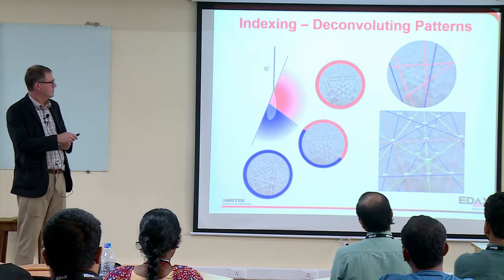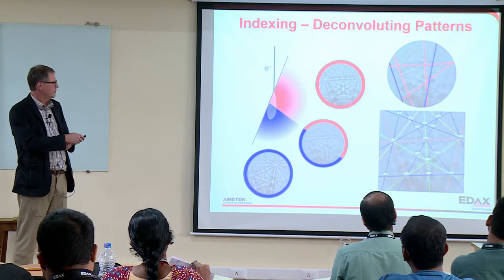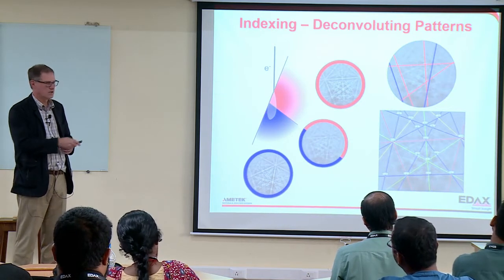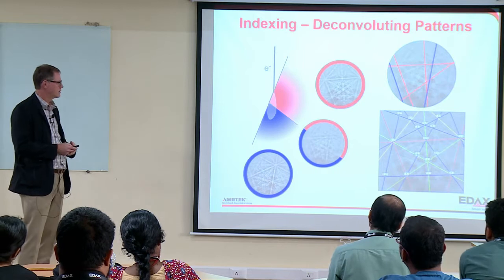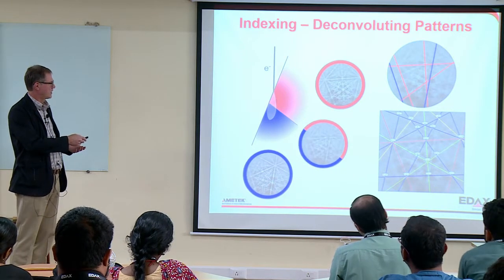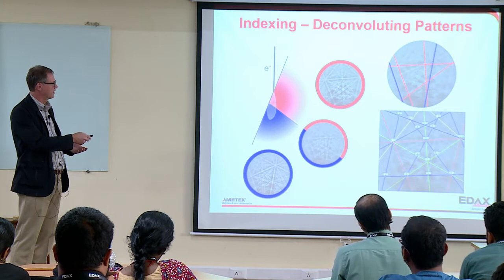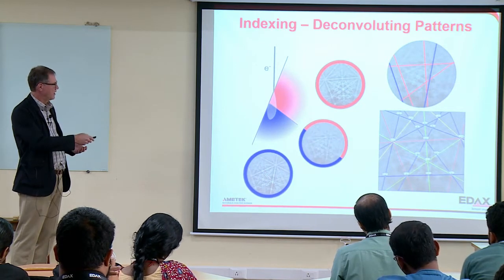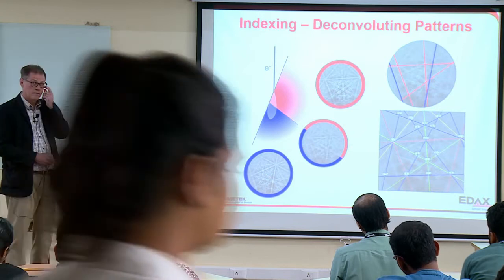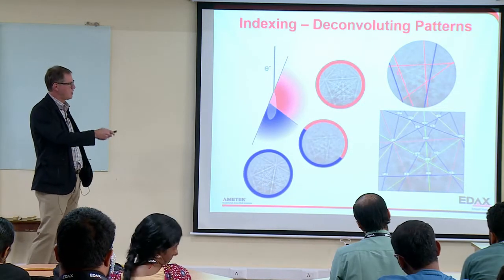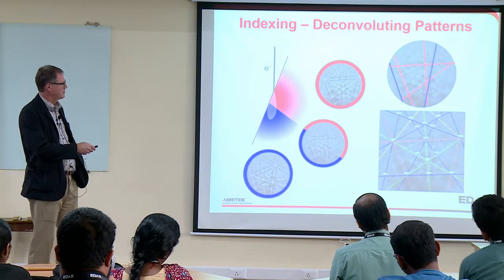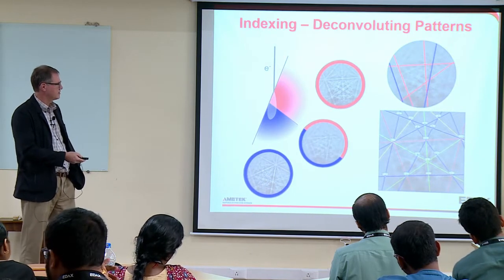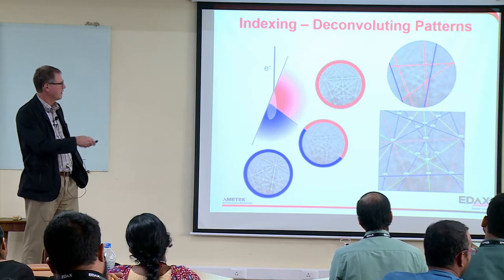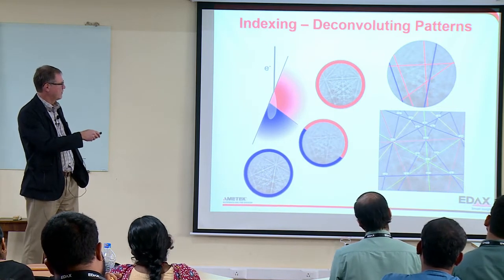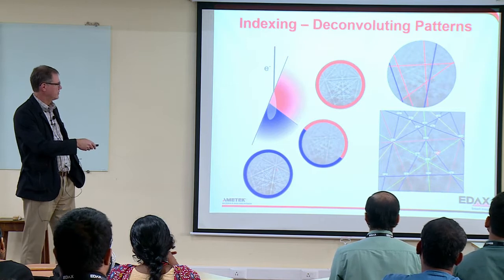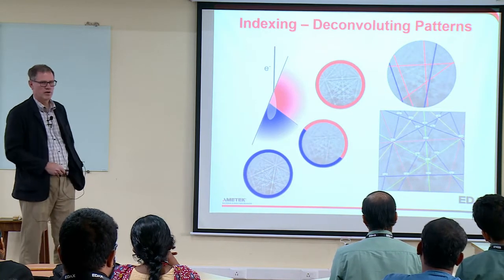EBSD can deconvolve mixed patterns. So if I have the diffraction volume containing two different grains, as in this example, then I have the diffraction pattern from the red grain, and the diffraction pattern from the blue grain. As I'm at the grain boundary, I'm going to get a mix of those two. But the way EBSD works is it will try to detect bands. And so in this case, I set it up to find 6 bands, which is not very many, but good for this example. So I found 4 for the red and 2 for the blue, and so it's going to index the pattern as if it were the red orientation.